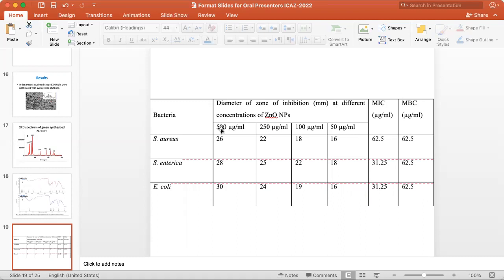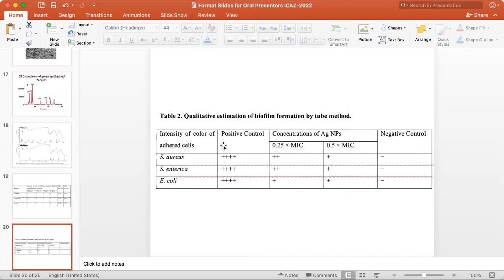In the agar-well diffusion method, there was a dose-dependent response. By increasing the concentration of nanoparticles, the diameter of the inhibitory zone also increased, and maximum inhibition was observed against E. coli, whereas for Staph aureus, when a concentration of 500 microgram per ml of nanoparticles was used, the inhibitory zone was around 26 millimeter.